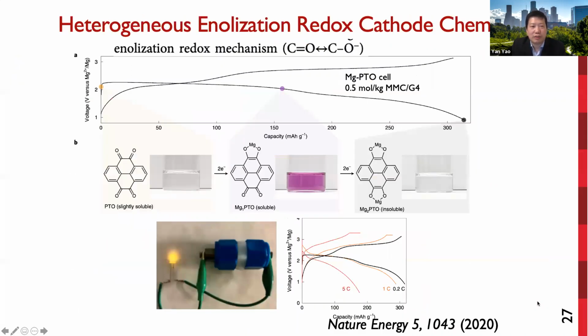In our recent work, we have demonstrated a heterogeneous enolization redox cathode chemistry to circumvent the ionic dissolution and solid-state diffusion challenges. PTO was again selected as a model compound due to its high theoretical capacity and solvent-free magnesium storage. So the voltage profile consists of 2 plateaus, each corresponding to 2 electron reactions. The average discharge voltage is about 2 volt, and the capacity is about 315 milliamp hour per gram. Both of these values represent one of the highest values for magnesium batteries.